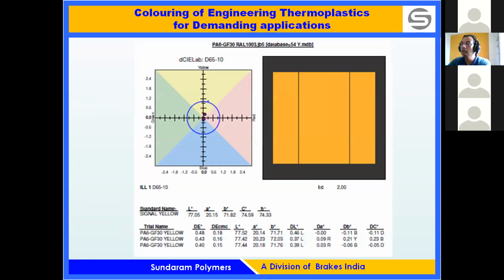This is the normal color report. Here we have measured the color value of a signal yellow standard, whose nearest RAL shade is RAL 1003. Signal yellow has an L value of 77.05, an A value of plus 20.15, and a B value of 71.82. We can see that the L value is above 50 and approaching the 100 scale, so the shade is lighter. A is positive, which represents a yellow-red shade, while B is 71, which says it is highly saturated with yellow. So the typical shade can be viewed as lighter, redder, and yellower.